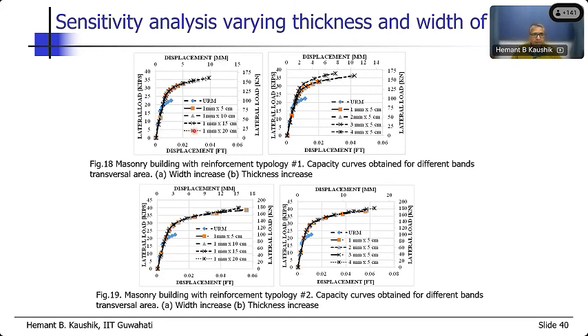So you can see here, very interesting thing that we observed, that it really did not matter what is the size of the steel flat. Even for the very low 1 mm by 5 mm, 5 cm steel flat, the performance was really nice. And we go on increasing this width of the steel flat, it did not matter. The strength was more or less same because the failure was occurring in the masonry. So masonry is weak. It does not matter how strong or how thick or wide this is. There was a minor difference when we used thicker steel flats, but then you can see here most of these results are lying along the same region.